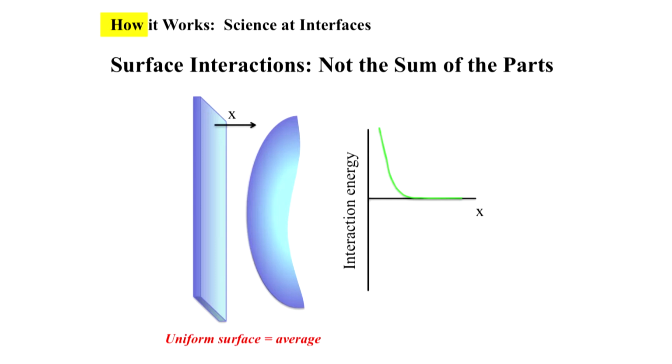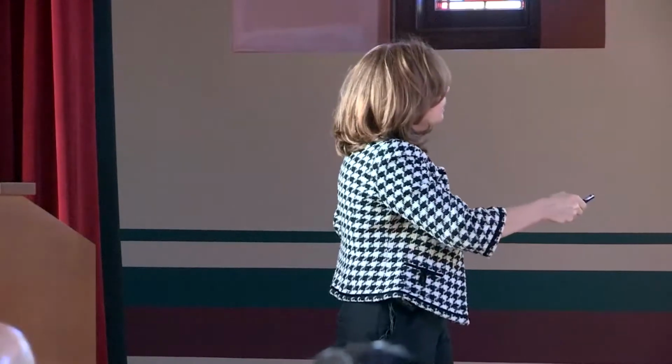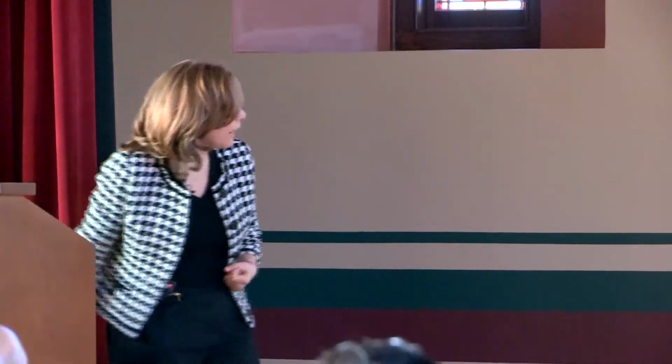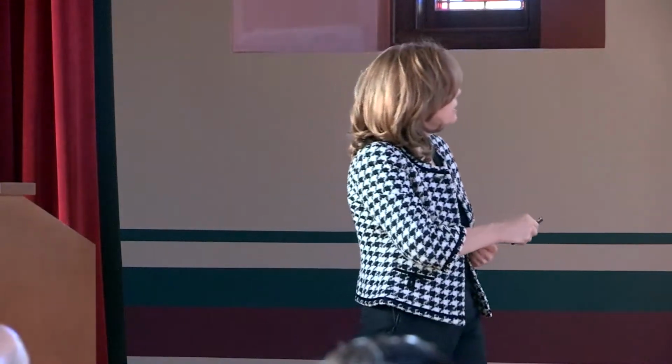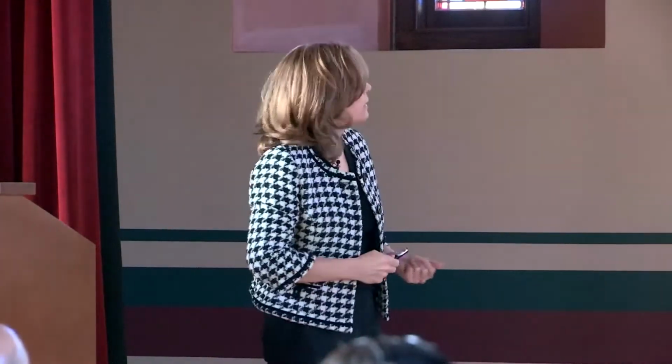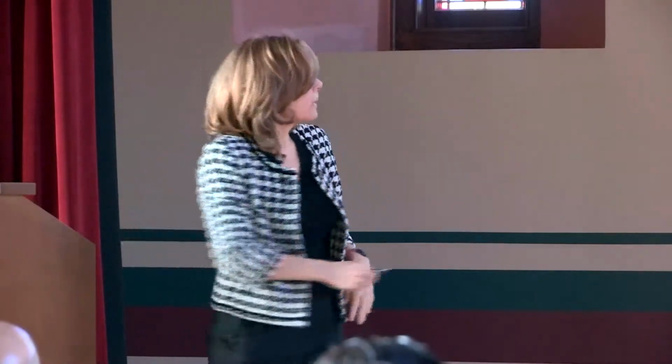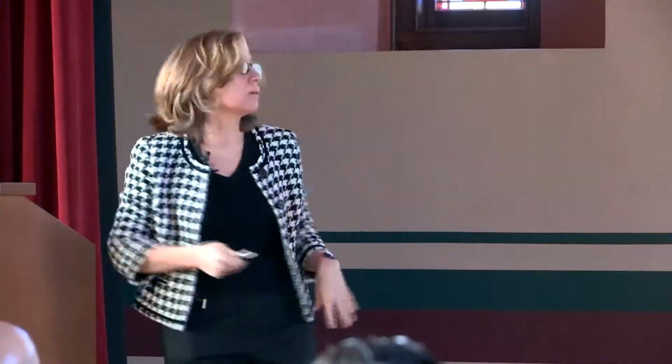And we can think about that, quantify it, by thinking about the energy in the system when we squeeze the surfaces together. We load it up, and that increases the energy of the system made up of the pair of particles or the pair of surfaces. Now, I can do chemistry, let's say, uniformly on that surface, and it would change the nature of the interaction. It may be that I can make this surface somewhat attractive towards the particles that I'm interested in studying. And in that case, when the surface is far apart from the particle, it may feel like it's pulled together. That would be represented here as an attraction because the system is doing work on me. I would have to pull on it to hold them apart.